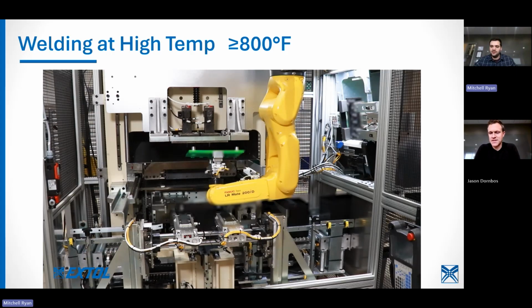Is the heat plate temp continuous, or do you heat it up when necessary? It stays continuous. Because we're heating up a large chunk of steel, we get that up to temperature. It can take anywhere from 10 minutes to an hour or 2 hours if it's a really large hot plate to get up to temperature, and then we just maintain it right there.